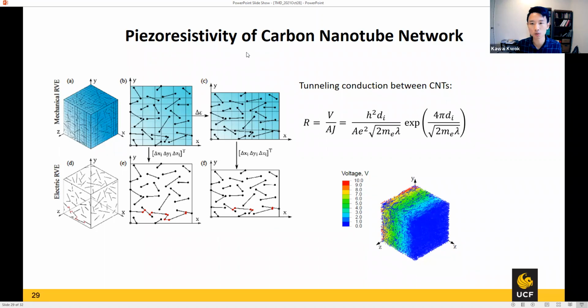This is a model that we came up with. Basically, it's an electromechanical coupling model. What we do is distribute these carbon nanotubes inside a volume, and then we stretch it. Because of the network deformation, all these carbon nanotubes, which are all conductive, will change positions. Some of them go out of contact, some of them get into contact. That is how the resistance changes, because the distances between these carbon nanotubes change as the strain is applied. At each strain, we can obtain the positions of all these carbon nanotubes and conduct an electrical simulation.